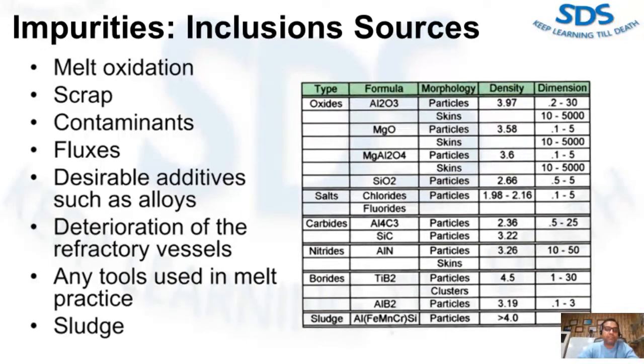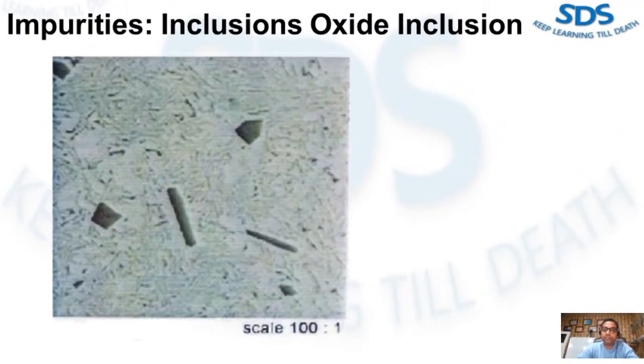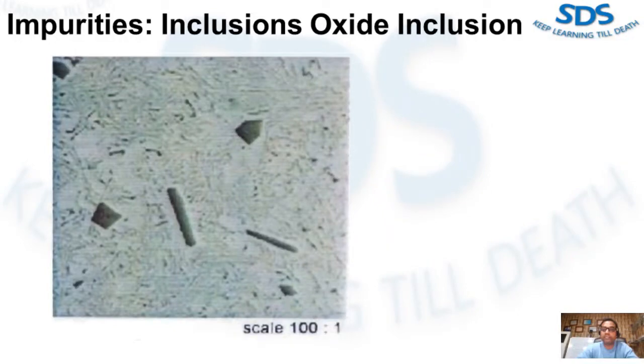The following table presents most of the types of inclusions that can exist in aluminum die cast alloy. These inclusions include a wide spectrum of density, size, and forms such as skins, discrete particles, and agglomerations. Oxides are the most prolific type of inclusions. Spinels, which are double oxides of aluminum and magnesium, exist in alloys where magnesium is present. Refractory inclusion compositions include silicon carbide, oxides, etc., arising from the deterioration of refractory vessels. In aluminum melts produced from prime ingot, aluminum carbides are often present as inclusions due to the electrolytic production process employed at the smelter.